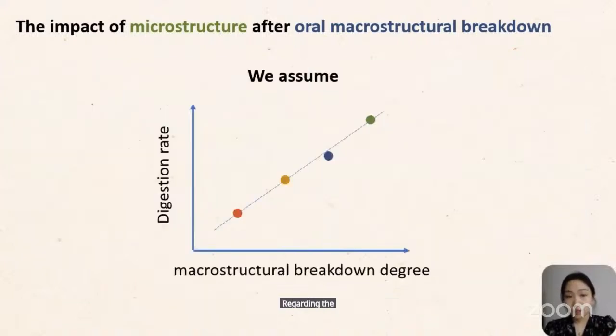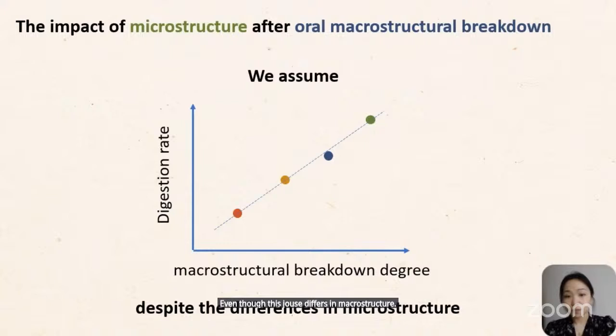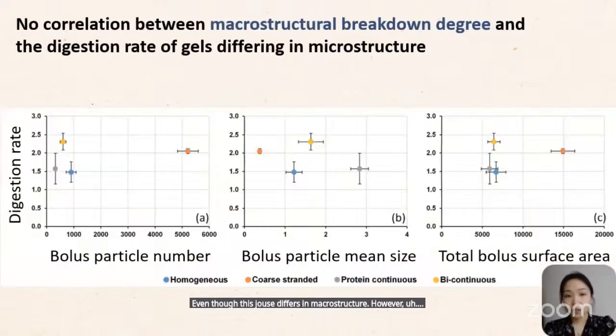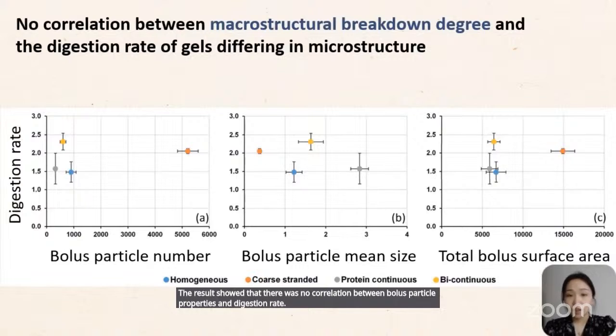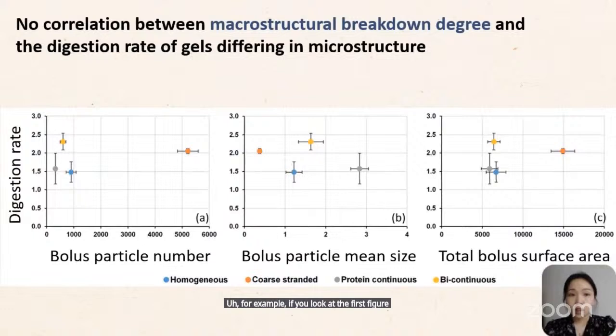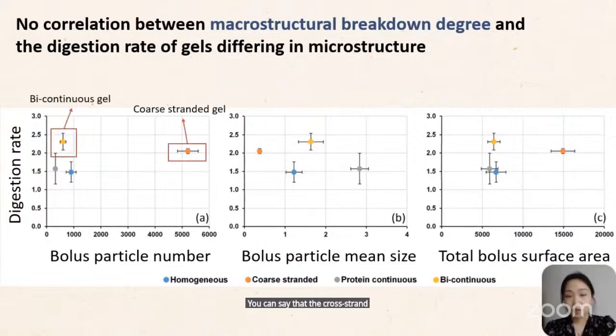Regarding the degree of increase in digestion rate, we assumed that after chewing, the larger the degree of macrostructural breakdown, the higher the digestion rate. For example, the gels with more and smaller bolus particles would be more easily digested compared to the gels with fewer and larger particles, even though these gels differ in macrostructure. However, the results showed that there was no correlation between bolus particle properties and digestion rate. For example, if you look at the first figure from the left, you can see that the coarse stranded gels have more bolus particles than bicontinuous gels, showing a larger degree of structural breakdown during mastication.